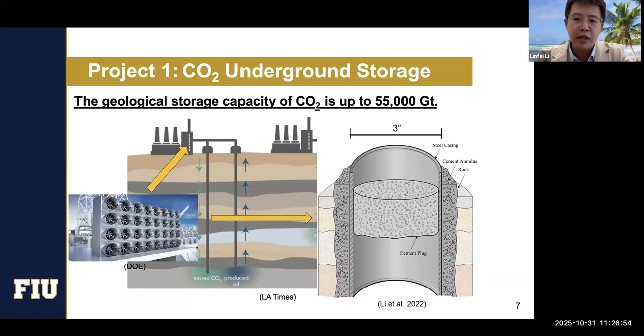But the problem is that this kind of cement has to be injected from the steel pipe, go all the way to the bottom, and flow back to fill all the gaps. Which means this cement material is very, very flowable, and it does not have any sand particles or aggregates in it. As a result, in the underground environment, with high temperature and high pressure, this very thin cement is very easy to get cracked. Once the cement gets cracked, well, the steel casing is only 3 inches in diameter. How can you send people 1 mile or 2 miles underneath to fix it?